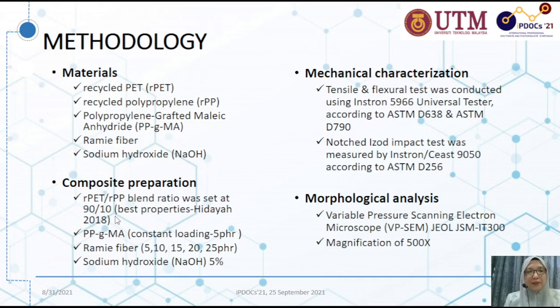Okay, for composite preparation, the recycled PET, recycled PP blend ratio was set at 90:10, which is the best ratio for mechanical properties according to Hidayah 2018. The mixture was then added with the PPGMA at constant loading of 5 PHR. The Rami fibers were introduced to the blend with different fiber loading from 5 to 25 PHR. And the sodium hydroxide we use at constant loading of 5%. The extrudate was cooled and cut into small pellets and dried for 24 hours.